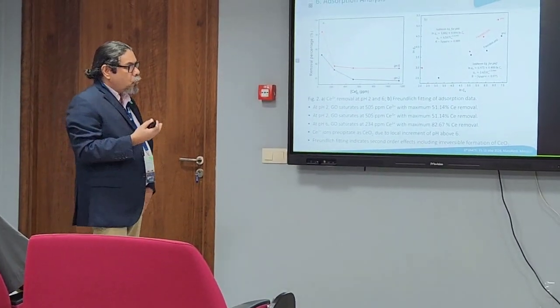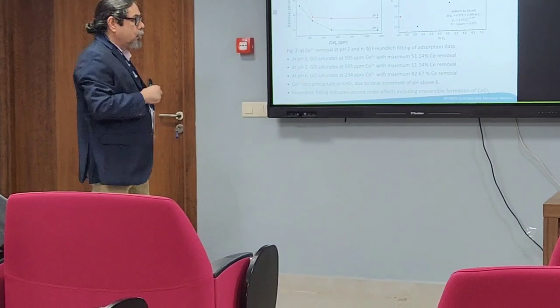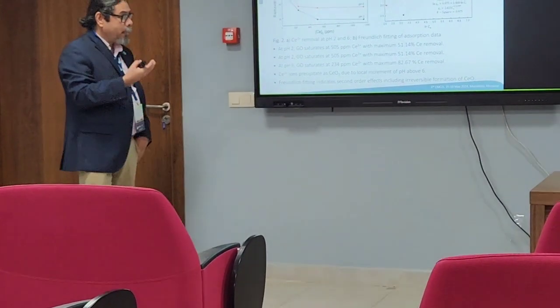We tried to do the fitting of these two isotherms, and the isotherms show an irreversible formation of cerium oxide-2, as we saw in the X-ray diffraction tests.